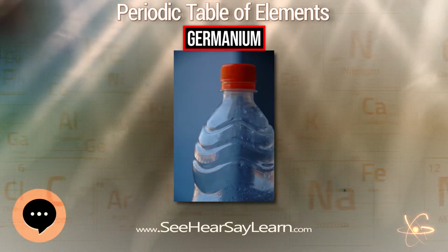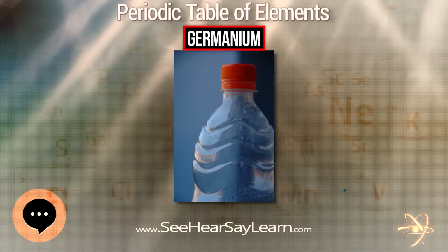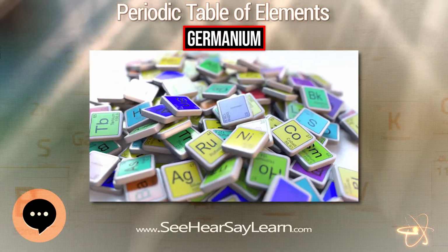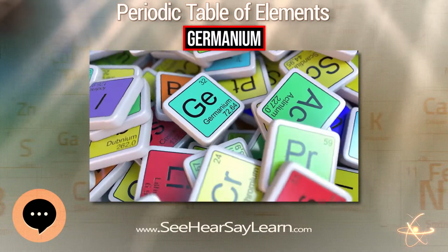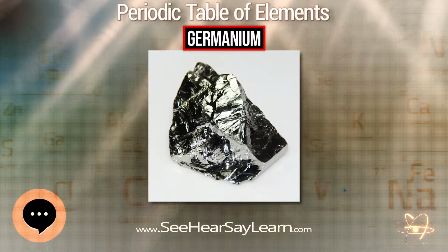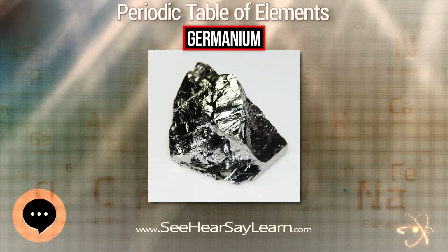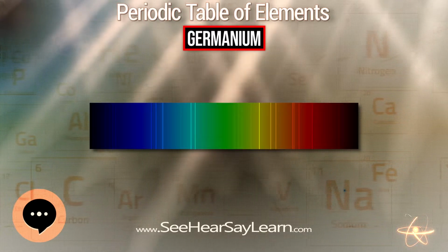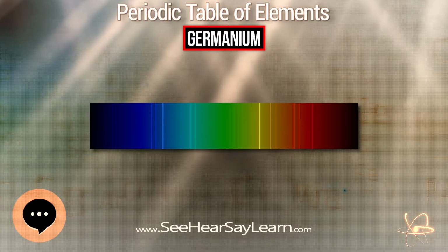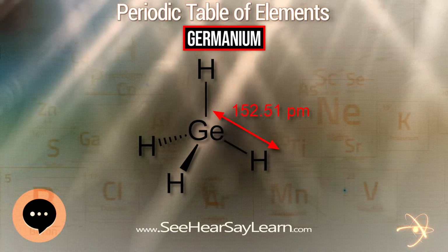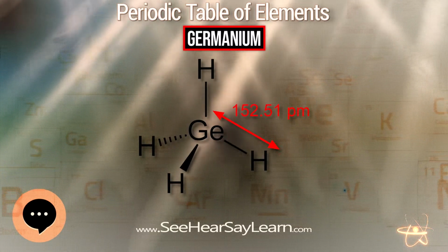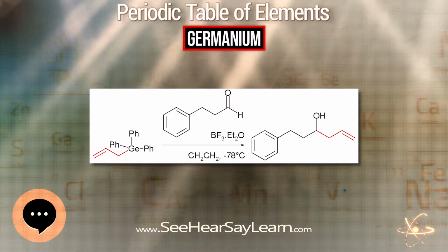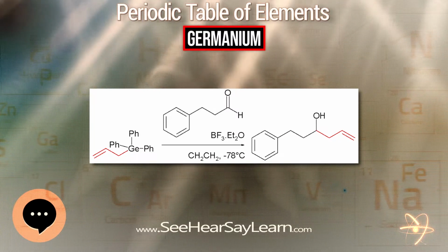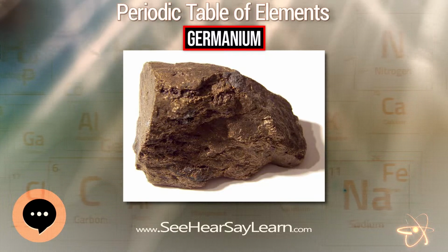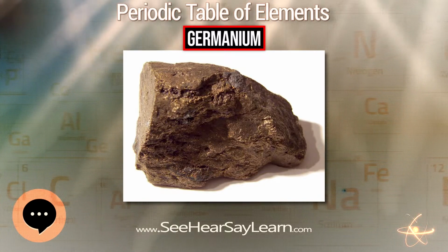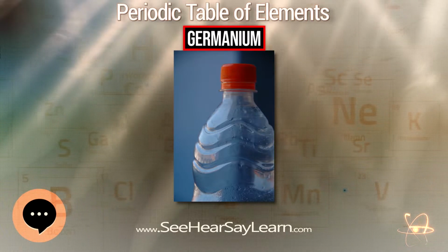A recent study found that at least 10,000 tons of extractable germanium is contained in known zinc reserves, particularly those hosted by Mississippi Valley-type deposits, while at least 112,000 tons will be found in coal reserves. In 2007, 35% of the demand was met by recycled germanium. While it is produced mainly from sphalerite, it is also found in silver, lead, and copper ores. Another source of germanium is fly ash of power plants fueled from coal deposits that contain germanium. Russia and China used this as a source for germanium.